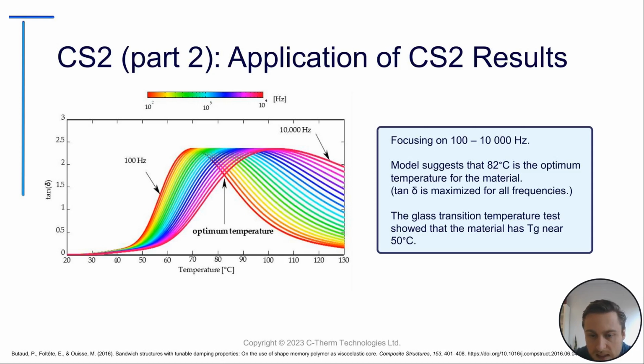I should note that the glass transition test suggested the TG was near 50 degrees Celsius, which is often used to predict damping performance, but it truly depends on what frequency you're considering. If your material is being vibrated at 1 hertz, yes, the ASTM standard for finding a glass transition temperature is probably the suitable manner for that. But really understanding how your material properties change with frequency is important for damping applications when we're usually trying to isolate specific frequencies.